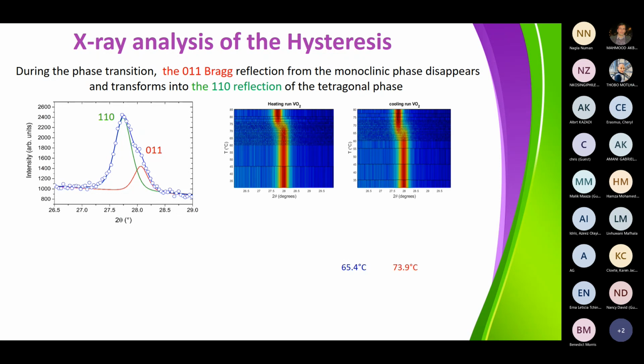You have to put two line shapes, one related to the monoclinic phase, the other related to the rutile phase. And you see here, we are increasing the temperature. There is only one reflection here, and in this area you see the coexistence of two reflections, and then there is only one, which is the rutile one. And why do you see something like this? Because it's a first order transition.